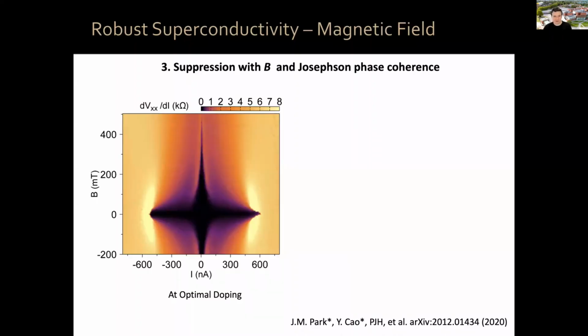If you go to optimal doping, a region where you have very strong superconductivity, and you apply a perpendicular magnetic field, you have a suppression of superconductivity initially very fast, and then you have a long tail up to very high critical field. I'll tell you more about this in a moment.